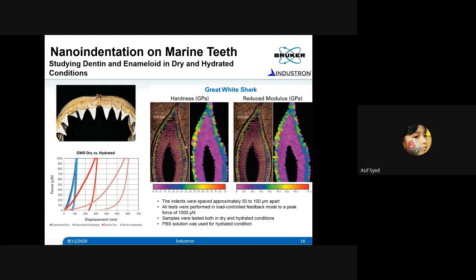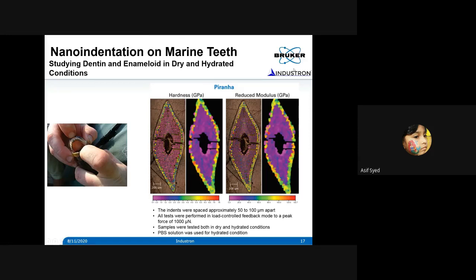Now if you do the same thing for piranha, you can also get the hardness and modulus map on the cross section of the tooth material. In most of these experiments, the spacing between the indents is 50 to 100 microns apart, and the maximum load applied is about 1,000 micronewtons, and they're all load controlled feedback mode type indentation experiments. I mentioned that the experiments were done both in dry as well as in a submerged liquid condition.